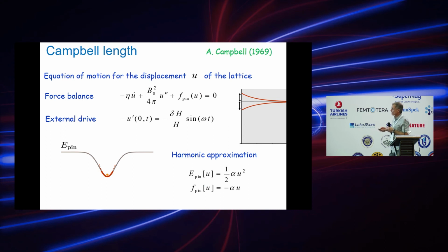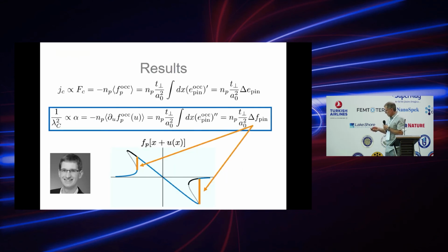If you try to do better, then you need actually to average over different vortices and different defects, because some vortex sits at the bottom of the potential, but others may sit at the place where curvature is maximal or another. So we have to perform this averaging over curvature, and as a result, we obtain that the average curvature is given by the jump, not in energy, but the jump in force. Average force is the integral of the derivative of potential and is given by the jump in energy. Average curvature is the derivative of force and is given by the jump in force.